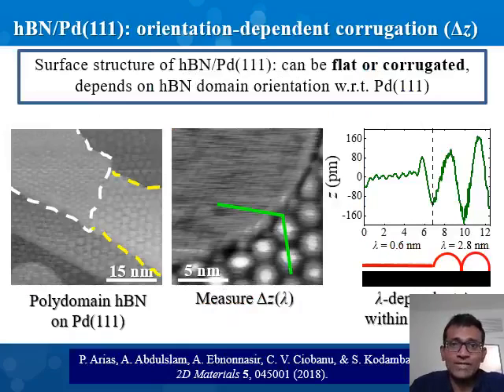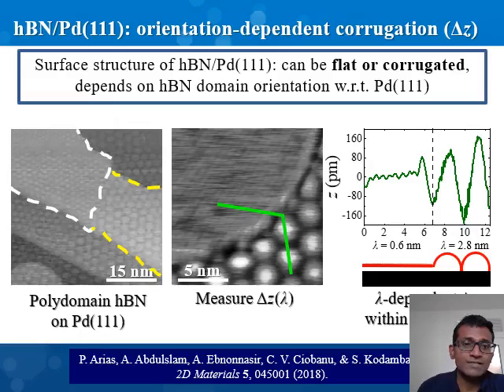For hexagonal boron nitride grown on palladium-111, what we have found is that the surface corrugation depends on the relative orientation of the hexagonal boron nitride on palladium-111. And in our experiments, we found, without any control over the growth parameters, that we obtain a polydomain hexagonal boron nitride, as shown in this scanning tunneling microscopy image here. And these dashed lines show different domains with different moire patterns.